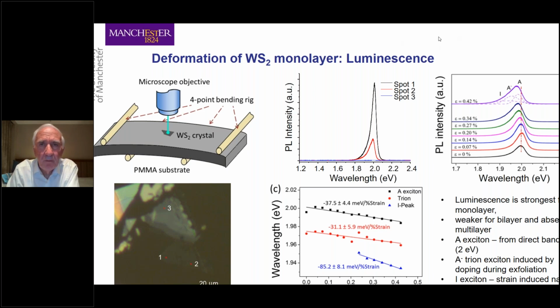And so, we saw some structures that were made by Professor Hersham, and you could see he was using it for a different reason, but if you want to use it for strain measurement, you could also do that with those sort of nicely distributed structures. And he showed particularly you could get high loadings of monolayer, and the monolayer is the best material for strain measuring. So it all sort of works out really quite nicely.